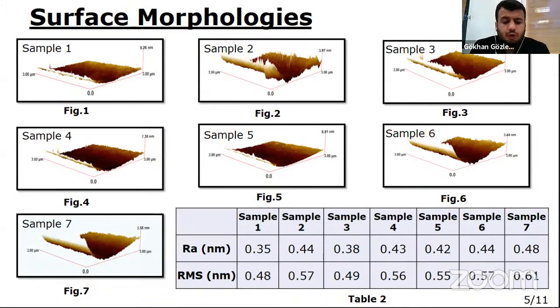The behavior of surface morphology of films at different thicknesses was examined in a 3x3 micrometer area with an atomic force microscope. AFM results show there is no significant change in the surface morphology by decreasing film thickness from 35 nanometers to 5 nanometers. The surface morphology of titanium dioxide thin films was very smooth, with average roughness lower than 0.5 nanometers.